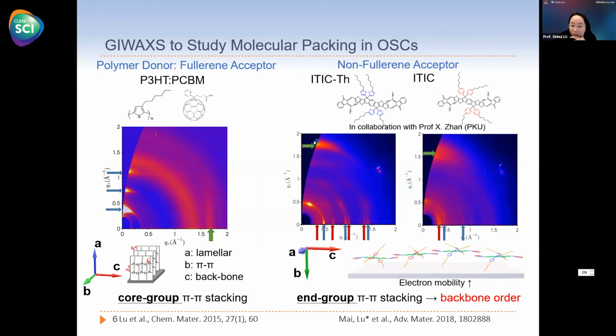Yes. So basically, the width of the peak in different directions tells us the length scale of the structural order in certain directions. For example, for this kind of banana-shaped peak, in the QZ axis, if we do a line cut, it tells us the correlation length, the distance for this kind of structure to lose its coherence. If we do a line cut in this angle axis, it means the orientation of this kind of structural order. So if it spans a longer angle, it means the orientational order is not good. Yeah, we can also extract this. This is in the reciprocal space, everything is in reciprocal relationship with the real space structure. So if it's wider, it means the structural order is shorter. If it's concentrated in discrete peaks, it means it's kind of a single crystal structure.